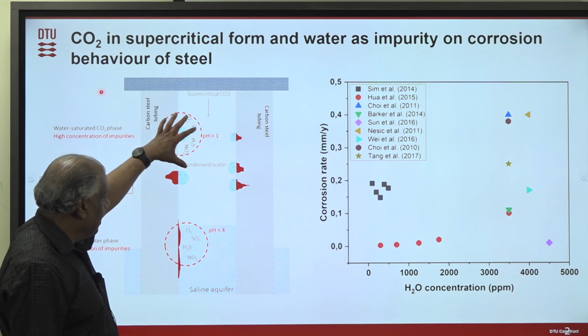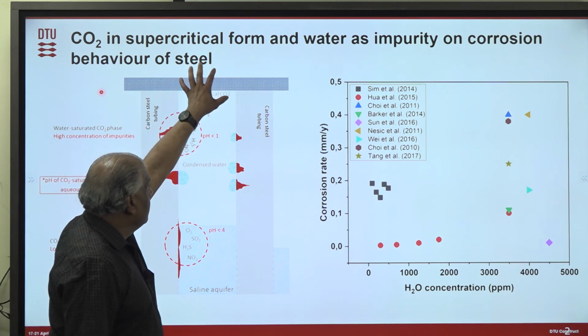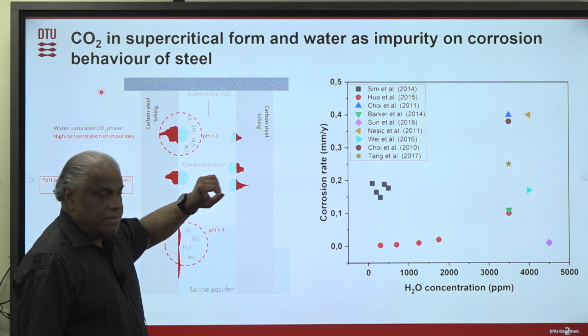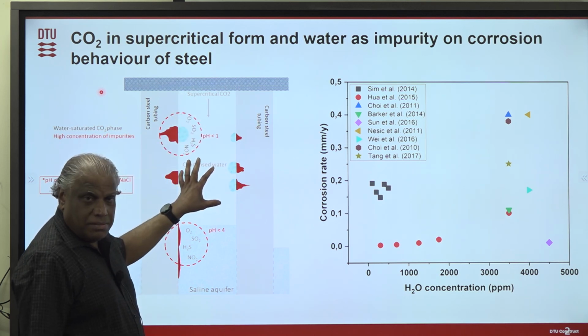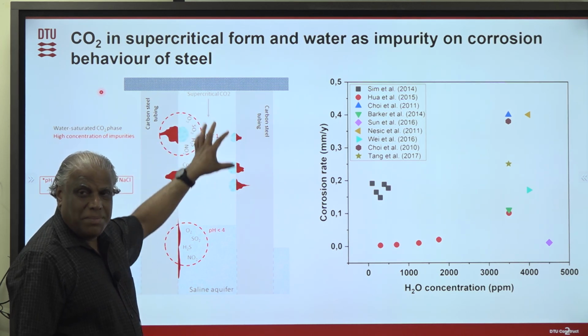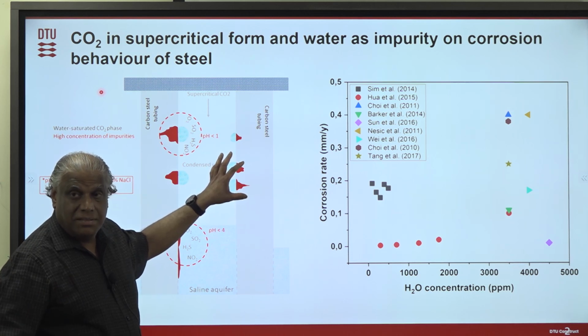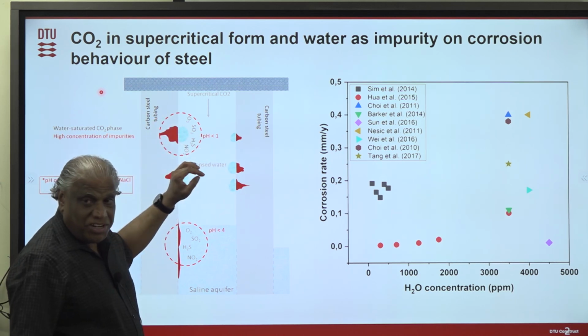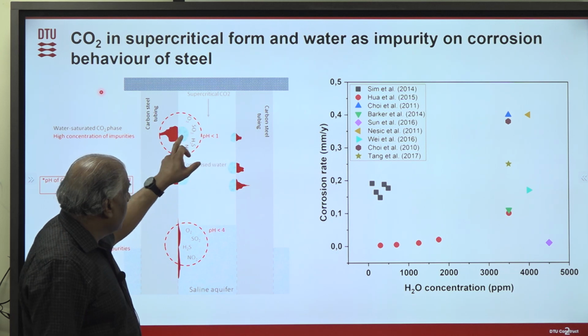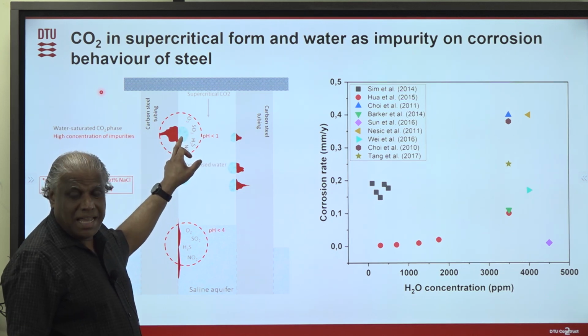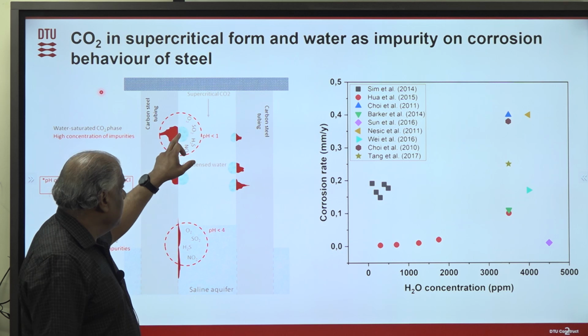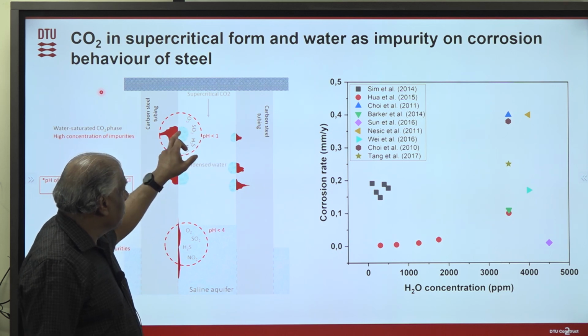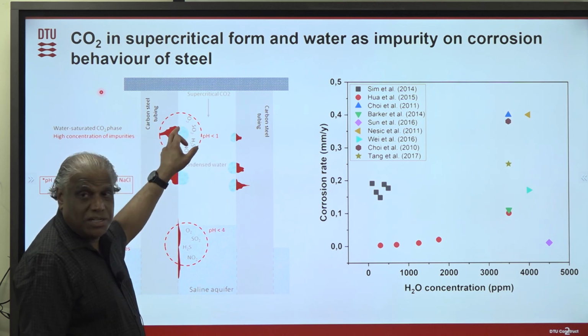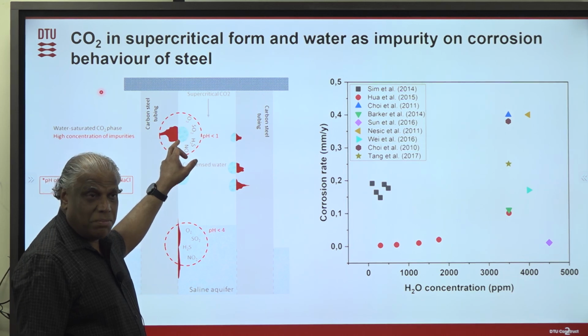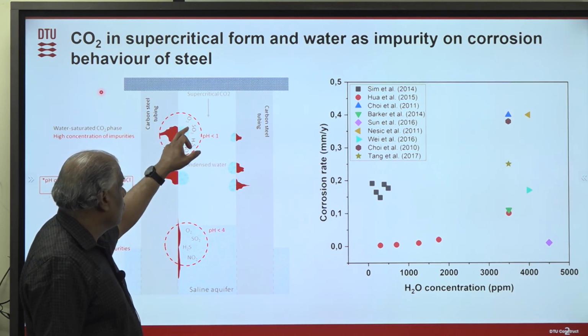So this is just schematically showing CO2 injected in the supercritical form. As it comes down, there will be a pressure drop. There may be pressure fluctuations. Those pressure fluctuations will make this water drop out, like a condensation. And this water will have a very, very low pH, because all these gases are dissolved in the small amount of water. So that will be a very low pH condition. You get a lot of corrosion problems here.